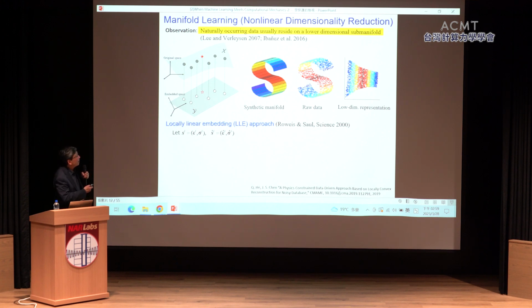Because right now our problem is we have the physical state that has been computed from the first level optimization. From the physical state, suppose it is here, and I'm searching for the proper data set that can be consistent with the physical state. Well, I don't really need to know the entire geometry or nonlinearities of this lower dimensional manifold. All I need to know is a few neighborhood points, and this is almost like using localized linear function to approximate higher order true solution, right? So if you just look at the local approximation, you can do something fairly simple. So that's the idea.